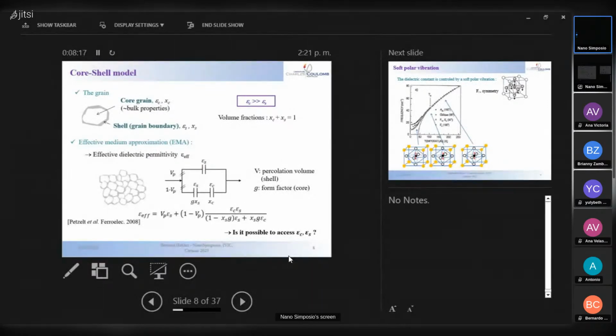And if you calculate the effective dielectric constant for this circuit, you find this formula, which is quite easy. This comes from this way, and this part comes from this way. Okay. But when you are measuring the dielectric constant by usual electrical measurements, what you are measuring is epsilon effective. You don't separate both components of the dielectric constant. So is it possible to access separately epsilon of the core and epsilon of the shell? That's the question. And yes, it is.